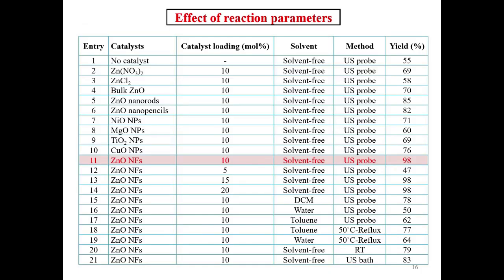These are the effects of the reaction parameters. The number of catalysts used by other researchers, and our group used zinc oxide nanoflowers. We have verified these zinc oxide nanoflowers from 10 mole percent to 5 mole percent, 15 mole percent, 20 mole percent in solvent-free condition, as well as in the presence of solvent.